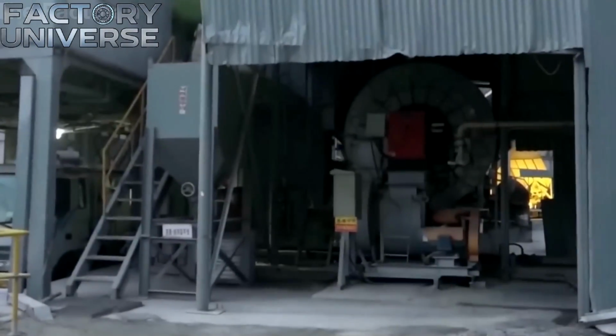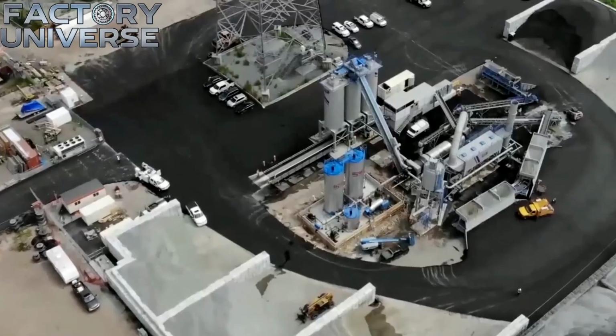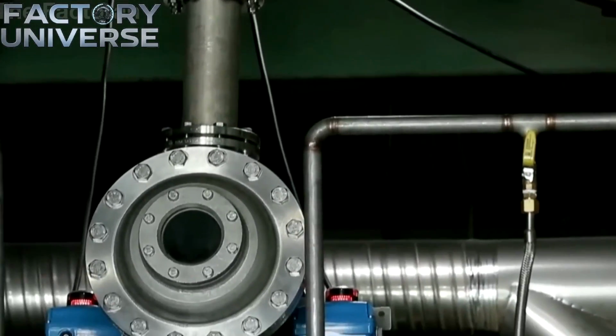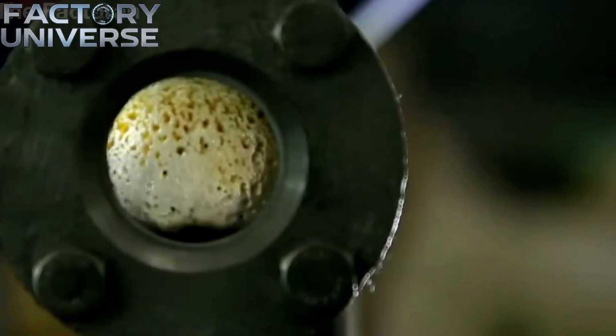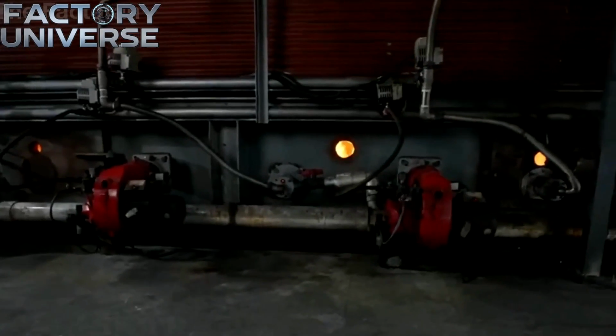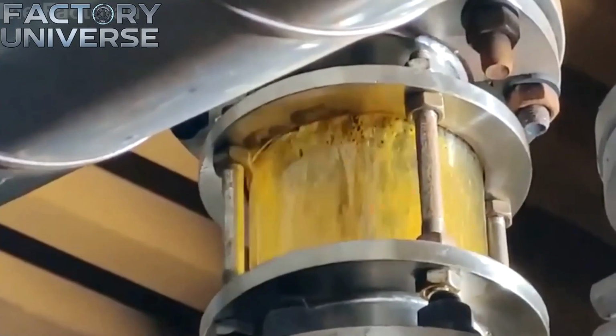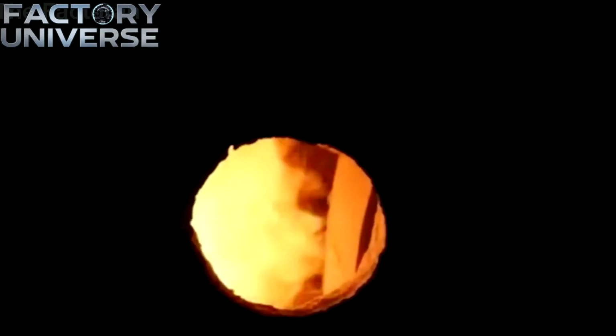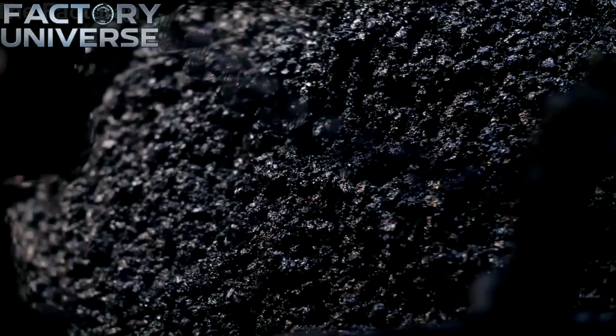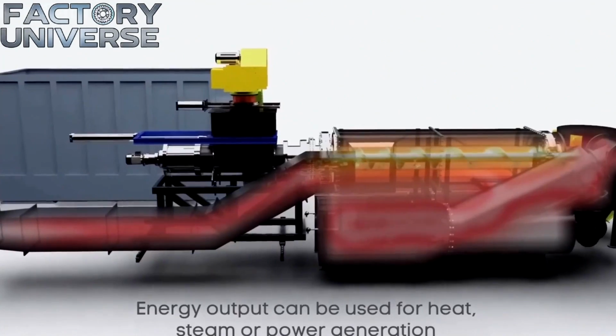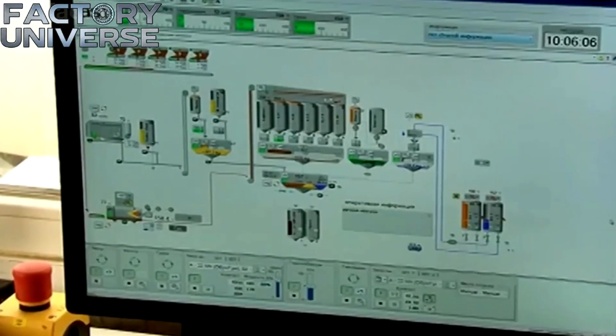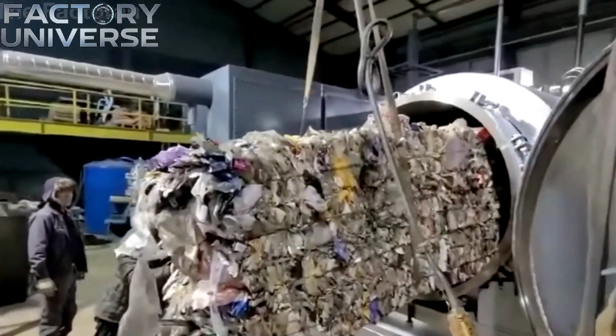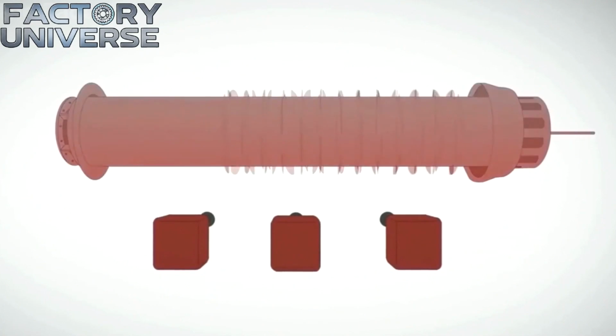One can notice how the solid material left inside the reactor is simultaneously transformed into carbon black. This carbon-rich solid can be utilized either as a solid fuel or as an industrial raw material for various manufacturing applications. On average, the process yields about 175 to 265 pounds of combustible gas and a remaining portion of solid carbon-rich residue for every 2,200 pounds of input. Most of the energy originally stored inside the plastic is preserved in the form of oil and gas instead of becoming an environmental burden. Transition to the next level.